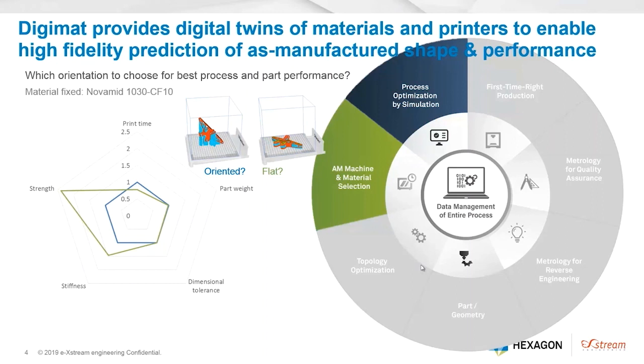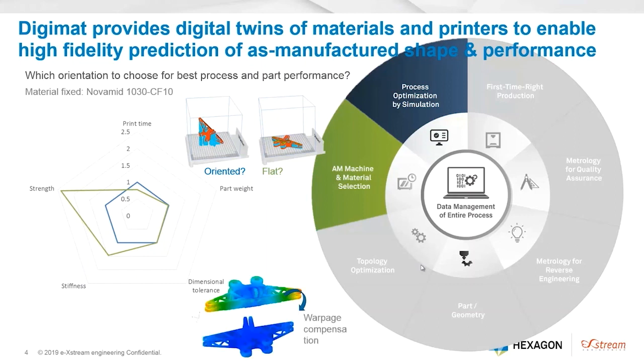What we want to achieve is a smart decision combining different factors such as print time, part weight, dimensional tolerances, stiffness, and strength. To define the dimensional tolerances, we first run a process simulation of the part for the 2 different printing conditions. The conclusion from the process simulations is that excessive warpage occurs by default and warpage compensation is required. Through warpage compensation, we are able to validate both printing strategies to meet the dimensional tolerances.